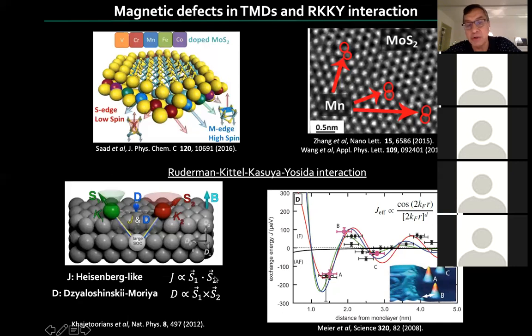It looks like this. J is proportional to S1 dot S2, the magnetic moments of the two impurities or magnetic species. And in the presence of a spin orbit, as I mentioned, which is large here, in addition to this Heisenberg-like term, there is an S1 cross S2, or non-collinear, or Dzyaloshinskii-Moriya interaction. So the first Heisenberg term, depending on the sign of J, will prefer to create ferromagnetically or anti-ferromagnetically aligned impurities. But it is spherically symmetric, right? They can be in any direction. Relative to each other is important, but once that happens, then the overall direction will not matter.